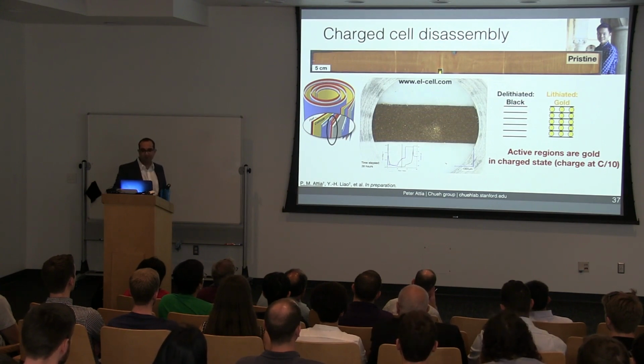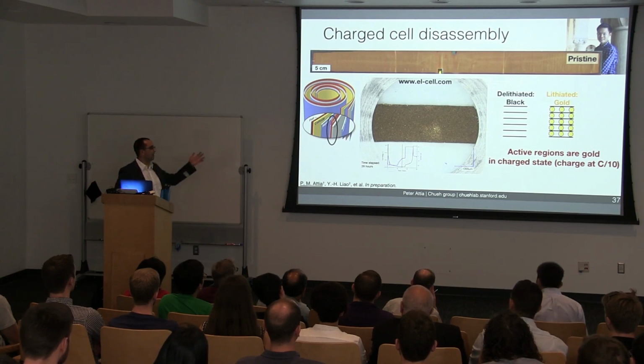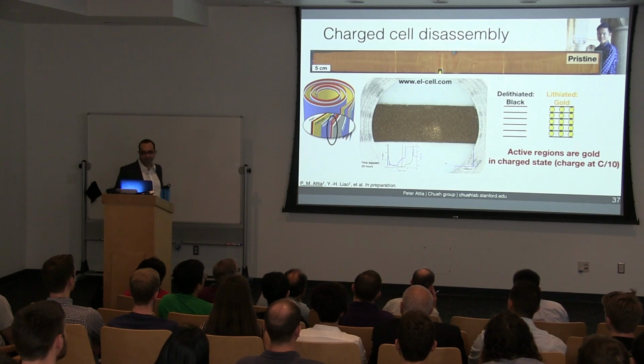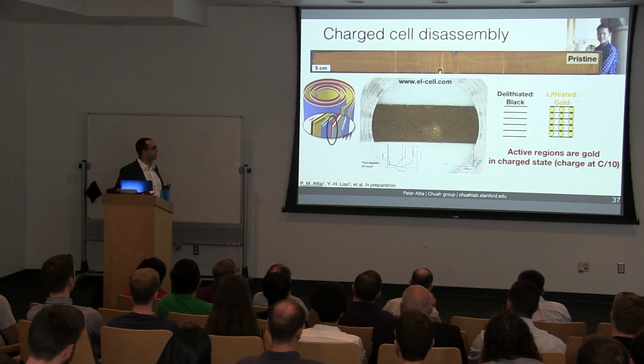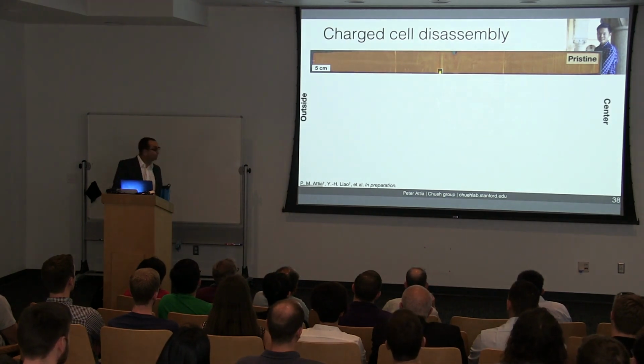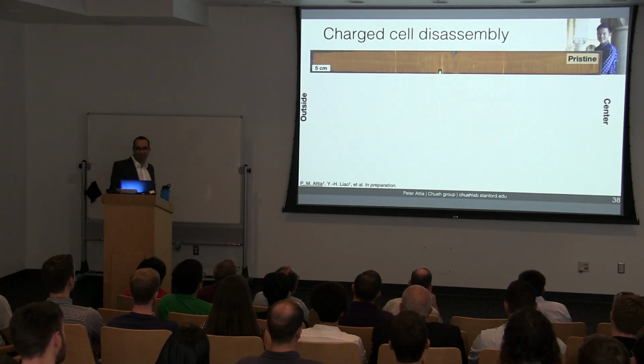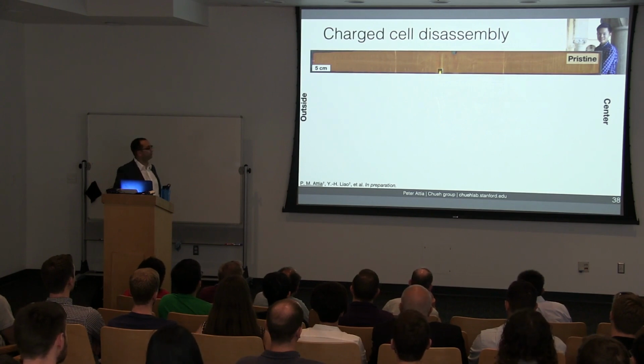So what we're going to do is disassemble the cells in the charged state. The idea is that the gold regions are parts of the electrode that are active, meaning they can be lithiated. And before we disassemble the cells, we charge them really slowly to make sure the lithium ions have all the time they need to insert into the active regions. So here's the pristine cell again. We can see it has this really uniform color across the whole electrode. I'll briefly mention that as we move from left to right, we move closer to the center of the cell.